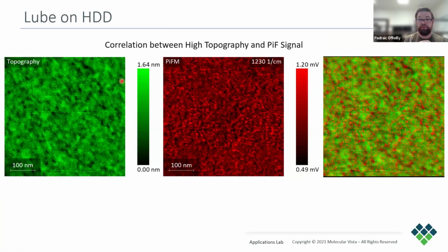Now when we overlay the topography here in green with the lube map in red, we see that the regions that are brighter for the lube map, so again these red, match regions that are darker in the topography image, which is green. So this tells us that the lube layer is thicker in the dips in the topography. And so again, even with this very thin layer of lube, we're actually still able to see the variations in its thickness. So this shows the benefit of PiFM for anti-stiction analysis, for example.